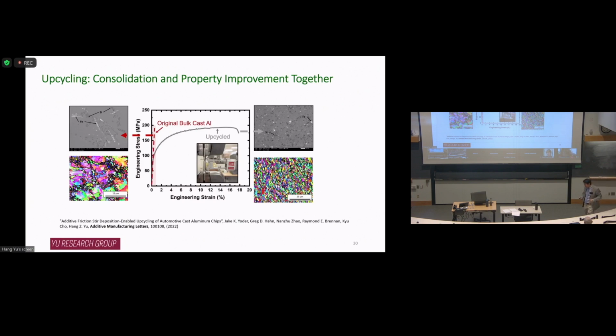But more importantly, we also have a second-phase particle change. In the original cast aluminum alloy, I have large, elongated silicon particles. I also have iron-based intermetallics. But during the stir process, because of the shear force, I'm breaking those large particles into small pieces. The particles become more spherical and well dispersed. So now this microstructure gives me better ductility and also some strain hardening behavior. So overall, I did not just consolidate the material; at the same time, I changed the microstructure during deposition so I can improve the ductility. We showed this work to Nissan people, and they said you should call this upcycling rather than recycling because you improve the ductility and energy dissipation.